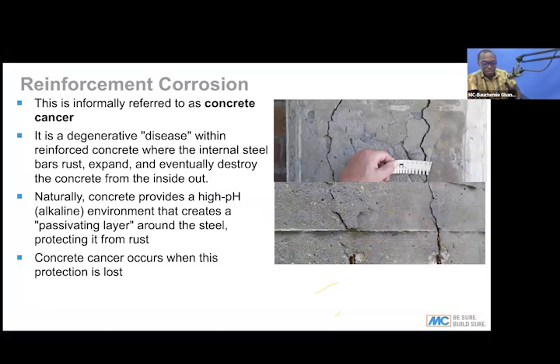Now, reinforcement corrosion, as I mentioned, reinforced concrete is a composite material, and the performance of the concrete depends on the reinforcement, and the performance of the reinforcement also depends on the concrete. Because when you cast concrete in the first state, concrete is basic, the pH is around 13, 14, but some external factors like carbonation can cause the pH of the concrete to be lowered. Now, when this process happens, the concrete becomes acidic, and this acidity breaks down the protection around the reinforcement, and that's what causes the setting of corrosion caused by carbonation. So once you have reinforcement in concrete and it's undergoing corrosion, it undergoes a process called expansion because of the corrosion. Now this expansion will cause the concrete to start breaking off, as you can see in the picture.